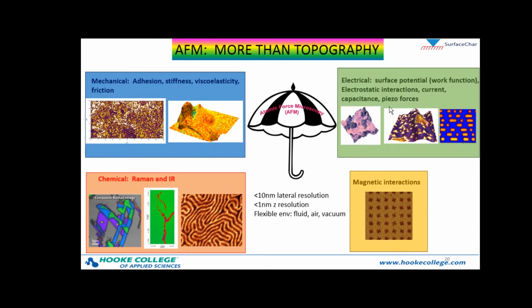We talked about electrical modes and talked about modes that AFM can map the surface potential or work function, electrostatic interactions, and current. It can also image other properties such as capacitance and piezo forces. Again, these two I did not include. We talked about recent advances in coupling chemical information like Raman and IR to AFM topography, and then also magnetic interactions using magnetic force microscopy. So we can map all these different properties in addition to topography, all on the nanoscale, with less than 10 nanometer lateral resolution and sub-nanometer resolution in Z.